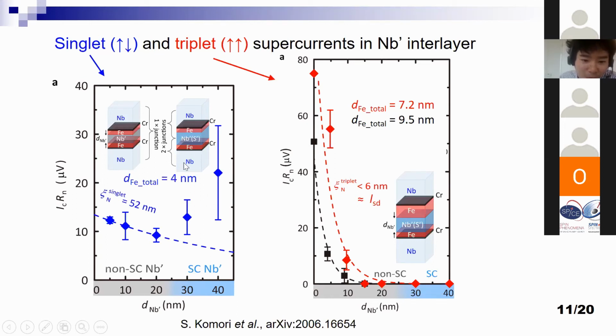This is because the interlayer of niobium basically forms a Josephson coupling with the top and bottom electrodes. So we have effectively two Josephson junctions in series here. And that basically reduces the thickness of the barrier layer compared with this single Josephson junction. So this formation of a double junction basically enhances the singlet Josephson current.